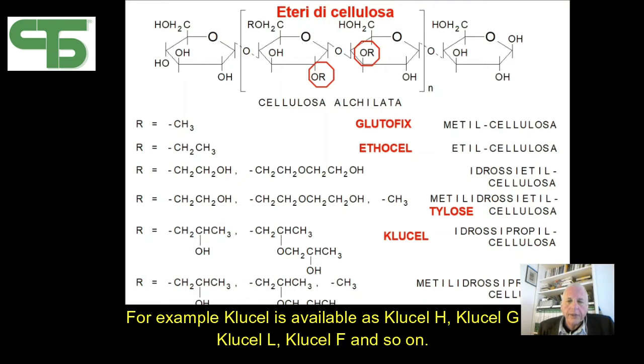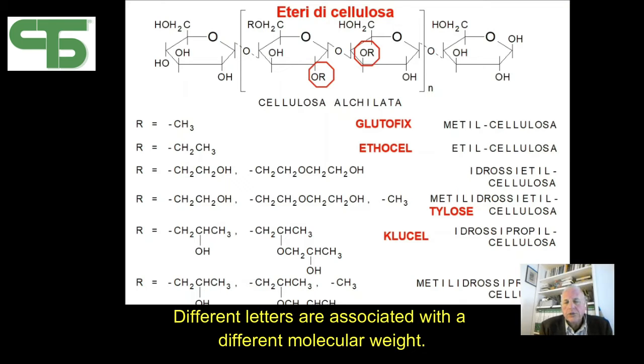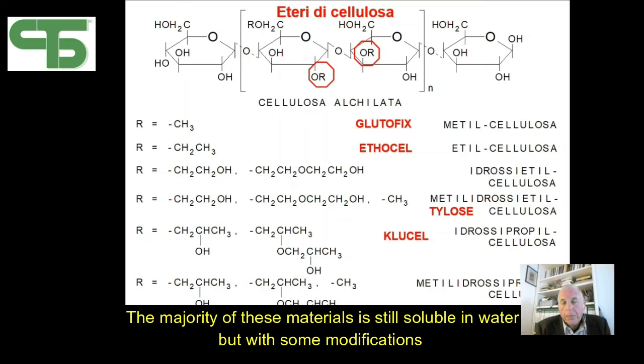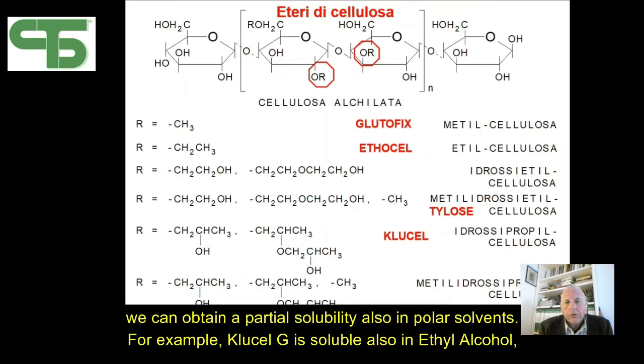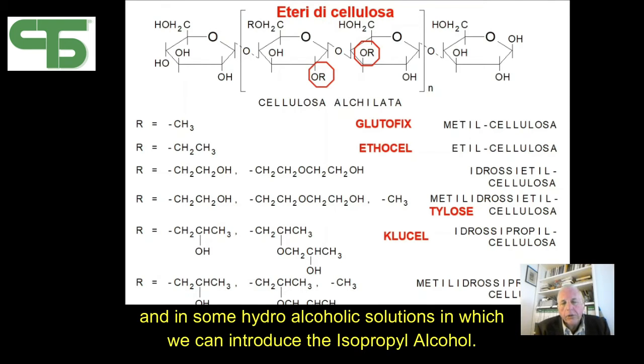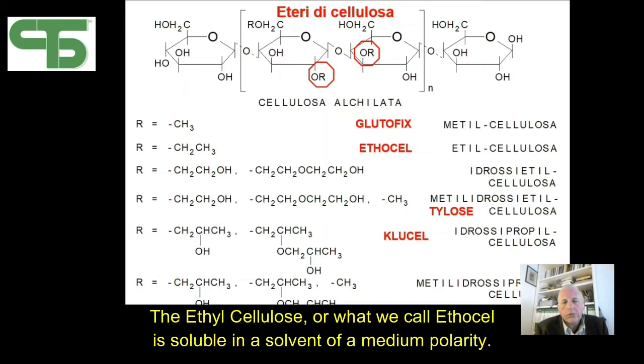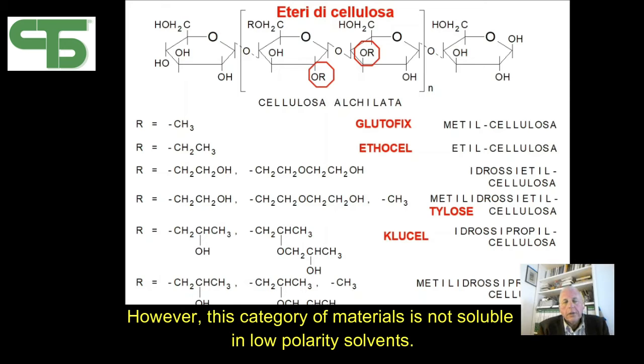For example, Klucel is available as Klucel H, Klucel G, Klucel L, Klucel F, and so on. Different letters are associated with a different molecular weight. The majority of this material is still soluble in water, but with some modification we can obtain a partial solubility also in polar solvents. For example, Klucel G is soluble also in ethyl alcohol and in some hydroalcoholic solution, in which we can introduce the isopropyl alcohol. The ethyl cellulose, or what we call Ethocel, is soluble in a solvent of a medium polarity. However, this category of material is not soluble in low polarity solvents.